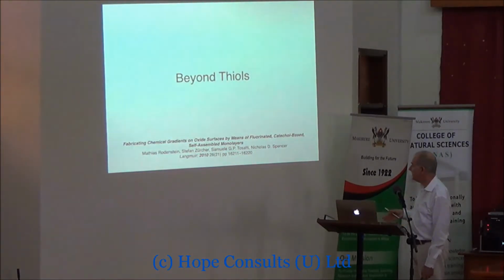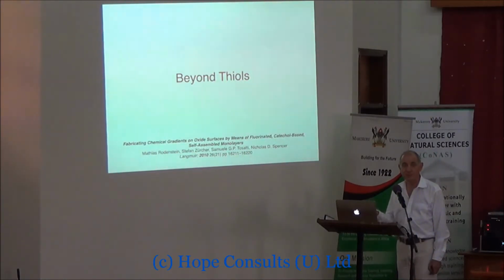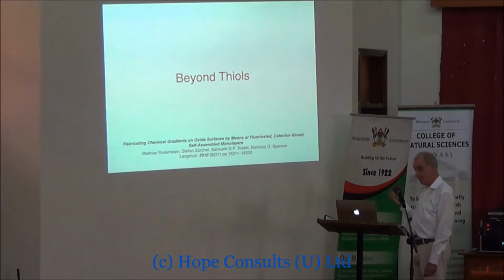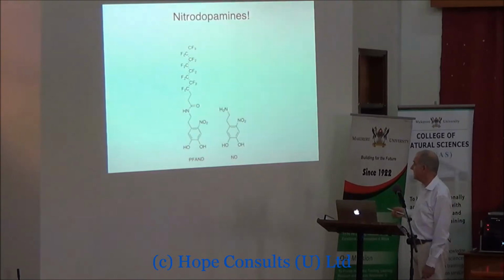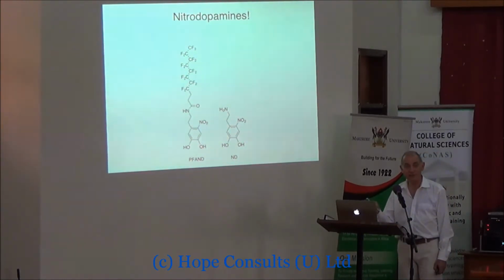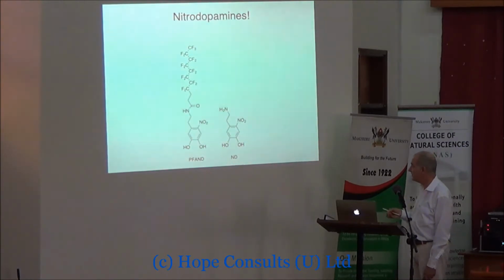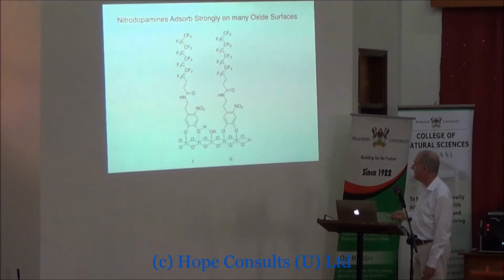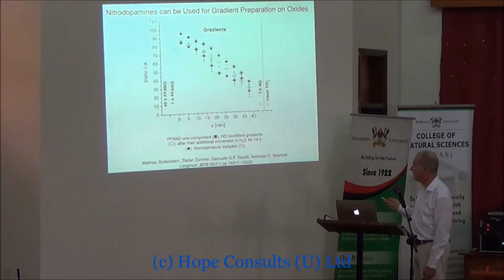Now, I briefly mentioned we adsorb other things than thiols on surfaces, because thiols will really only stick to a restricted number of expensive metals. If you want to functionalize something like titanium or iron, then you use different surface chemistries. And what's very good for titanium and iron is these nitrodopamines. This is based on the chemistry that mussels use when they stick to rocks in the sea. So they make very strong bonds with all kinds of different surfaces. And we've made them in hydrophobic varieties and hydrophilic varieties, and we can actually make a hydrophobicity gradient using these things too, by the same dipping process I talked about with the thiols.